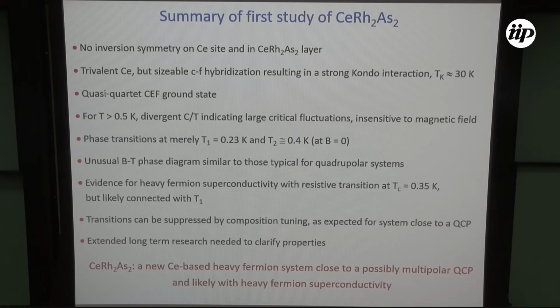So I come to the summary of what we did. We performed the first study of the compound CeRh2As2. It has the special property that there is no inversion symmetry on the cerium site, in the CeRh2As2 layers. It's a trivalent cerium, but with a sizable Ce-f hybridization, resulting in a strong Kondo interaction of the order of 30 Kelvin. We have a quasi-quartet crystal field ground state. For T above 0.5 Kelvin, we have a divergence of C/T, indicating large critical fluctuations, which are not purely magnetic ones, because they are increasing much too slowly, and which are insensitive to magnetic field, which could also be an indication that the fluctuations are not dipolar but quadrupolar.